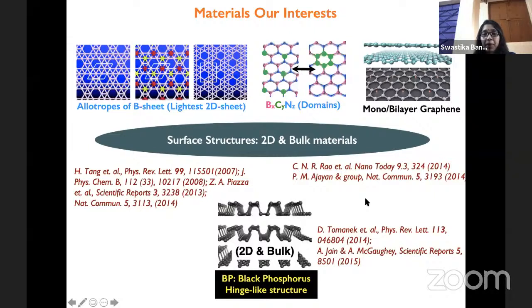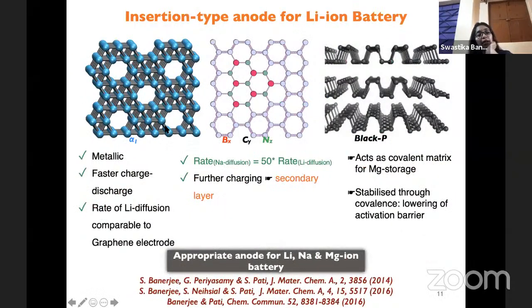We find that the lightest 2D sheet, which is the boron sheet, is actually very good in terms of lithium metal storage. The second one is good for sodium, and the phosphorene is very promising for magnesium ion. And we find this boron sheet is actually metallic in nature. So it's very easy to charge and discharge because the electron insertion and extraction is very fast. And the rate of lithium diffusion is also comparable to the graphene electrode. So it is promising for lithium ion storage, as the insertion type anode for the lithium ion battery.